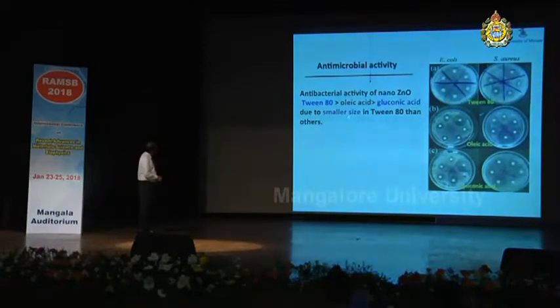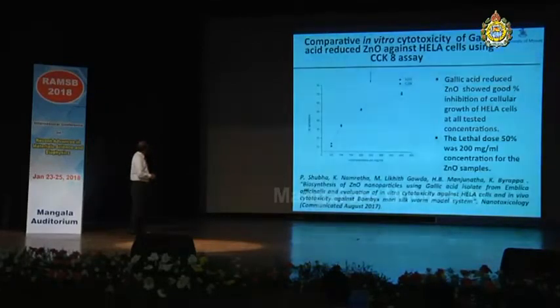And this is because Tween 80 gives very small particle size. So the smaller the size of the nanoparticles, higher would be the biological activity, which I also showed with the zone of inhibition in one of the earlier slides.